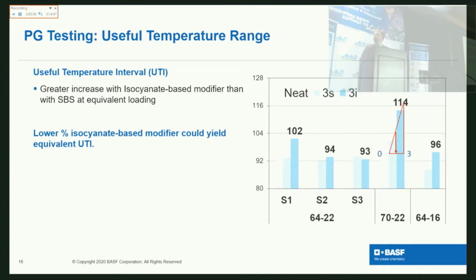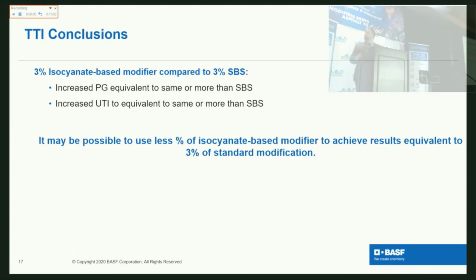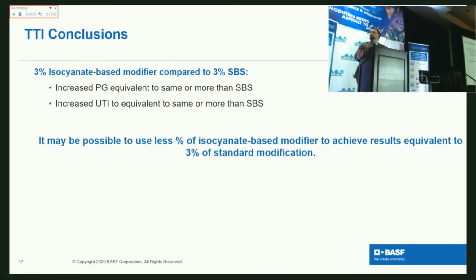So again, with that, what we found was UTI expansion on some asphalts of up to 114 degrees with just isocyanate modification. Okay, so comparing the two, and again, this was just comparing the everyday usage, right? SBS to isocyanate. And we found that with both, it could increase it equivalent to, or at least the same as SBS, okay?